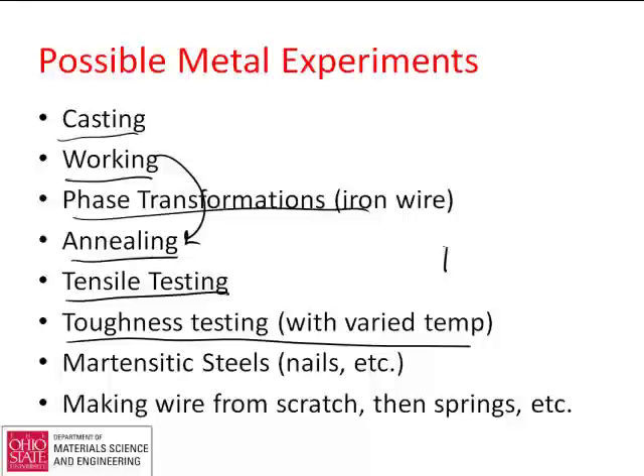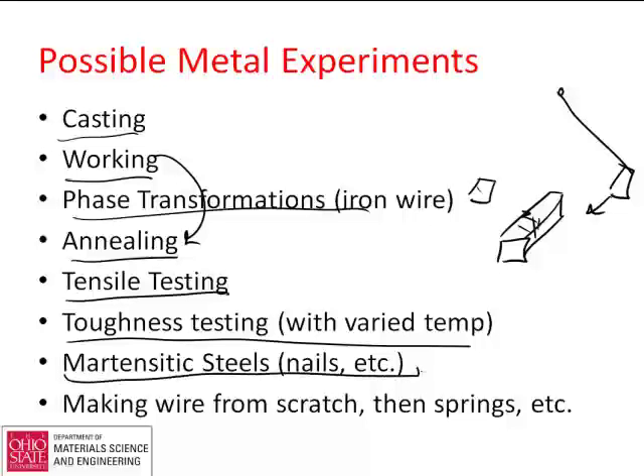Real easy way to do this is you can instrument something with something called a Charpy impact test, where we basically take a little bar, looks like this, put a little notch in it. And then what we do is have a hammer that comes through, and the hammer is on a pendulum like this, comes through. We can thwack this thing and then see how high the pendulum comes back on the other side. And that loss in height is basically how much energy was absorbed in breaking the bar. And that is another thing that could be very easily implemented, very nice destructive demo you could do in a ninth grade classroom. With steels, we can make martensite, we can do nails, we can temper them or harden them, some great stuff.